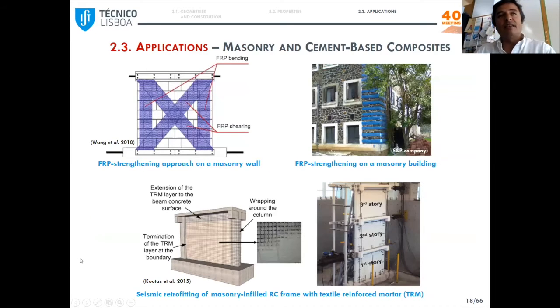And finally, you can see here another application, in this case of FRP sheets in masonry walls, bonded vertically or in a cross shape, so for flexural and shear strengthening. And below, a more recent alternative to the so-called conventional FRP systems, which are the textile reinforced mortar systems, which are more compatible with the masonry substrate.